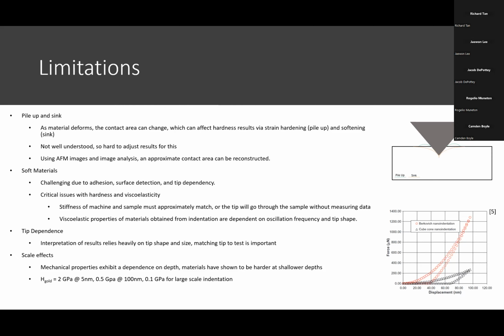Another limitation is using it on soft materials. Soft materials are intrinsically challenging because they have adhesion, surface detection is difficult, and there's a high dependency on the tip. There are also critical issues with measuring hardness and viscoelasticity. For hardness, you want your tip stiffness and sample to approximately match, or else the tip will go through the sample without measuring any data, and that's never good - you want your data. Second, the viscoelastic properties obtained from nanoindentation are very dependent on the oscillation frequency you use and the tip shape, so you have to account for that.